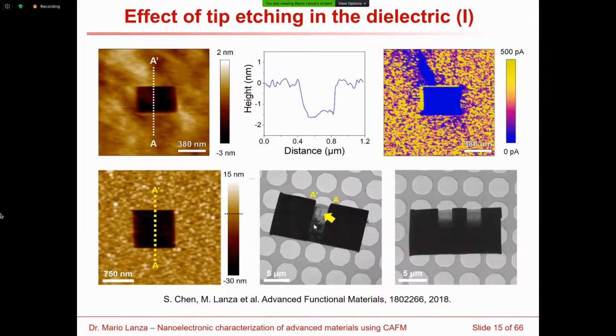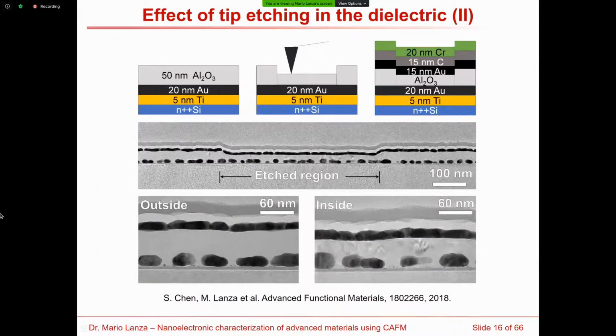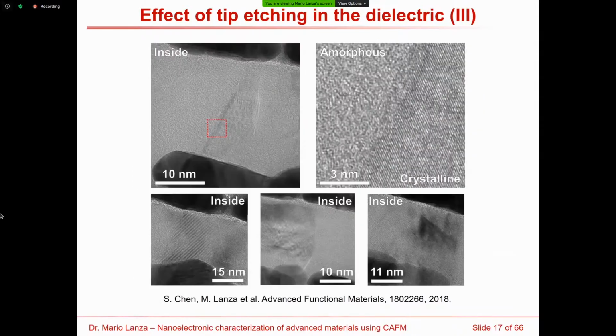This can also be seen in the TEM images, actually. If we do cross-sectional analysis of the etched region, for example, here, you can see very clearly, we have aluminum oxide where we etch and we cut with the TEM everywhere, and you can see the etched region. And if we zoom in on this region outside and inside, we can see very clearly that there are changes. There are some black particles that, if we focus on them, we observe they are a phase change. The material that was amorphous has polycrystallized, probably due to the high temperatures produced during the etching by the friction of the tip with the sample. We have demonstrated this with some simulations: some materials like silicon can become amorphous when we etch them, and the opposite, some amorphous oxide can become polycrystalline due to the temperature.